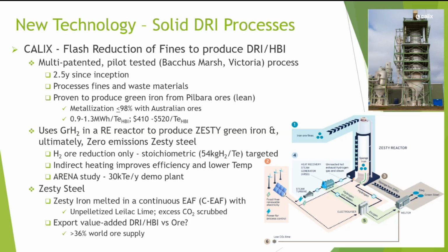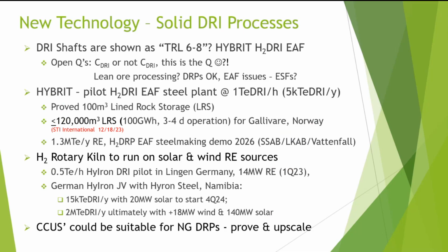And they have a process ongoing with their zero CO2 lime process, which is how this all started. They were producing zero CO2 lime. And they will combine all of that to put the zesty steel process together. Amazingly, the solid DRI processes only show TRL 6 to 8. I'm assuming it's because of the HYBRIT hydrogen process, and also the open question of whether we should maintain carbon in the DRI or not.